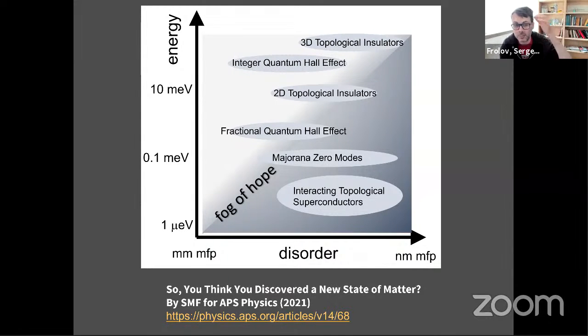And it summarizes my thinking in this very qualitative rough diagram where I put some topological phases, the famous ones, versus energy of the phase. So the higher the energy, the higher the temperature, let's say, that we can see them, and disorder. So disorder, good disorder is on the left and the bad disorder is on the right. So that makes a triangle in the upper part where we want to be. We want to be here with high energy and low disorder. And that's where we find some of the things like quantum Hall effects, topological insulators can be seen at room temperature. And there is no doubt that those phases have been demonstrated.